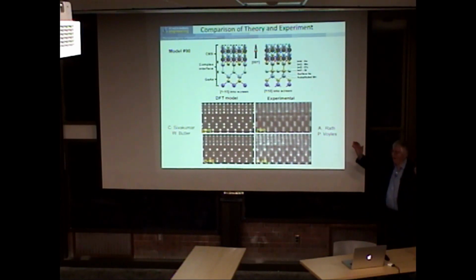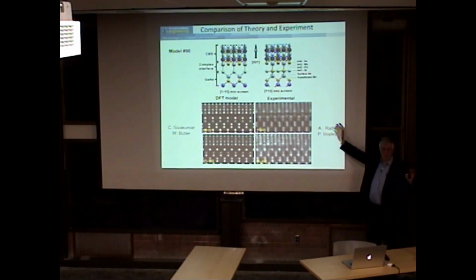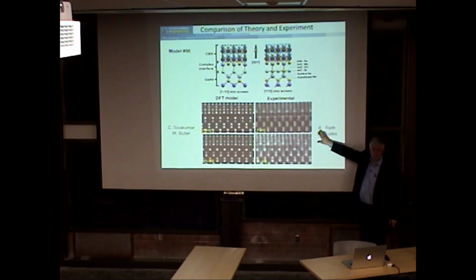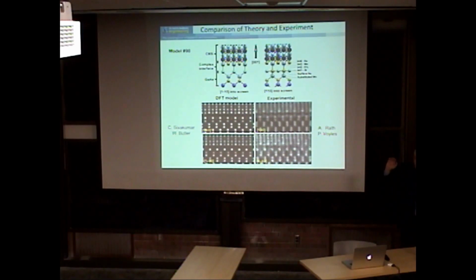But I mean, you do all of this with what the model does. I say all the things are subtle, and one of the biggest problems was with the EELS data. They couldn't see silicon, so it was very difficult to say where the silicon atom was. And that's why you're trying to use the relative intensities in this image to say what could be silicon, what was not silicon.